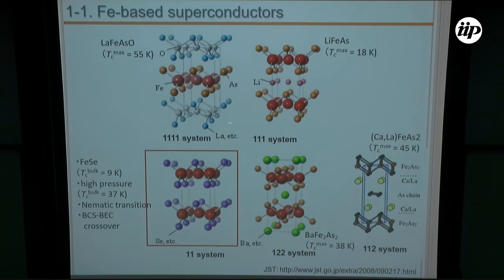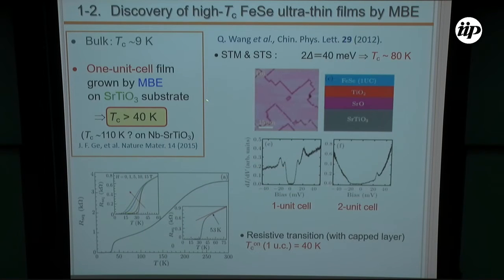Among the numerous iron-based superconductors, iron selenide, with a TC as high as 9 Kelvin, has the simplest crystal structure without blocking layers. However, this simple-structure compound has various new phenomena fascinating many researchers. One of the most exciting and attractive phenomena of this system is its high TC superconductivity in thin film form, which was first discovered by Professor Xue's group in Beijing 5 years ago.